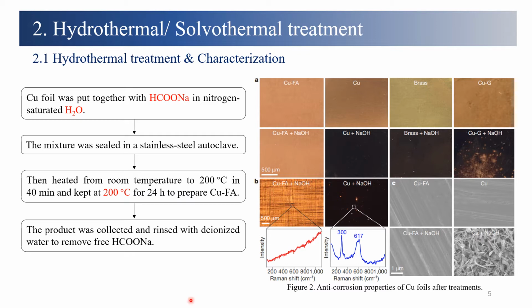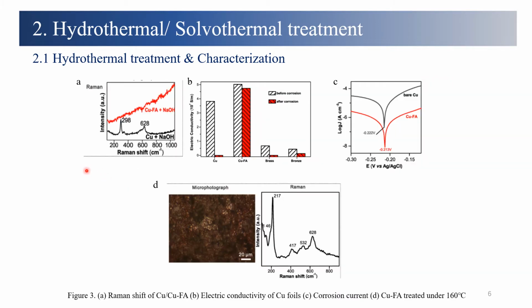The copper formate showed a good luster after exposure in base solution. However, others without treatment did not show good resistance. The Raman band here came from the copper oxide species, which only appear in bare copper. Moreover, it showed good physical properties.